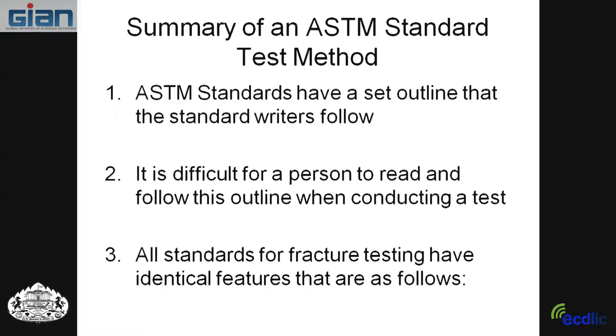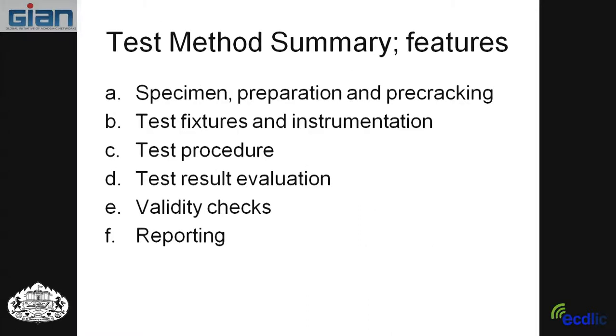All the standards have identical features, which are pretty much like this. You need to get a specimen, prepare the specimen, and almost all the fracture mechanics specimens need a pre-crack. A pre-crack is a crack that is induced by fatigue loading, and it's thought then to be mathematically sharp, so it fits the K calculation idea or the crack tip stress field idea if it's theoretically sharp. So it's introduced by cracking.